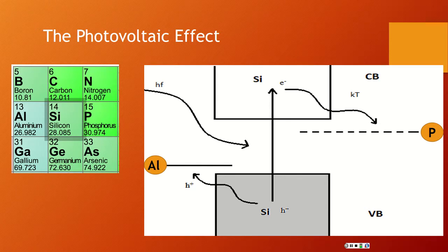Through non-radiative processes, that electron can decay down into, in this case, a phosphorus atom, which is an N dopant, and the hole that was left behind can transfer over to the aluminum or P dopant. That's pretty much what I'm trying to see with my study: some indication that there's transfer of charge, negative electrons, over to the N dopant.